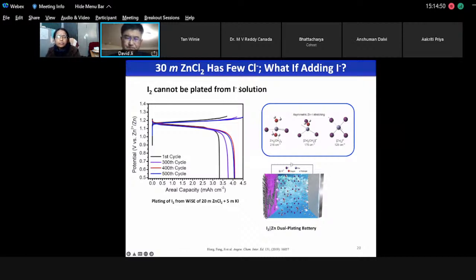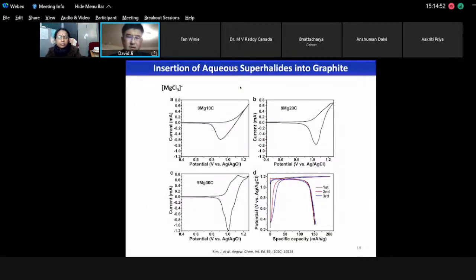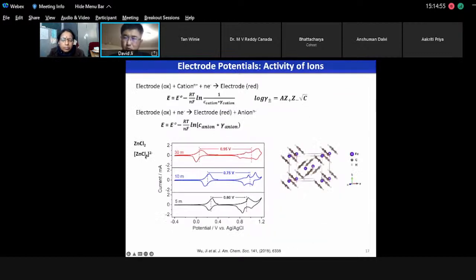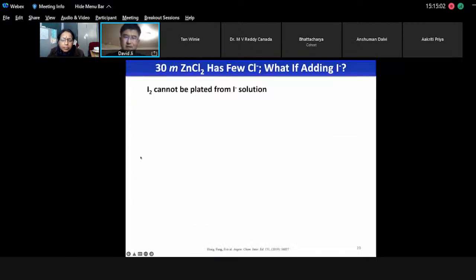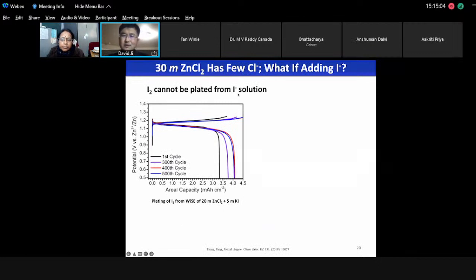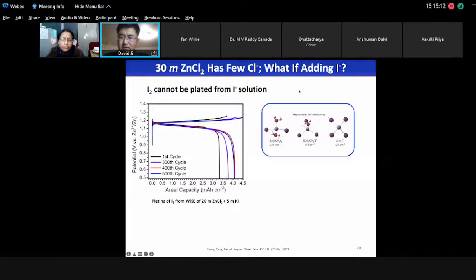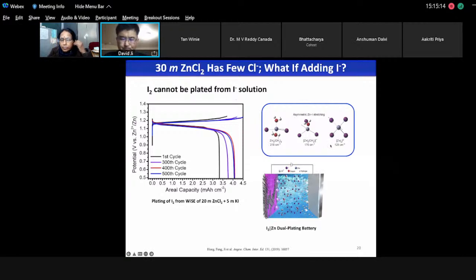And we have learned that in this system, we don't have free chloride. So if we have iodide added into this system, probably we will not have free iodide either. That's the case actually. If you add potassium iodide into a concentrated zinc chloride electrolyte, you don't have free iodide. It's mostly zinc iodide complex ions, right? So we have an interesting system, which is a dual plating battery. The cathode is iodine plated, and the anode is zinc plated.